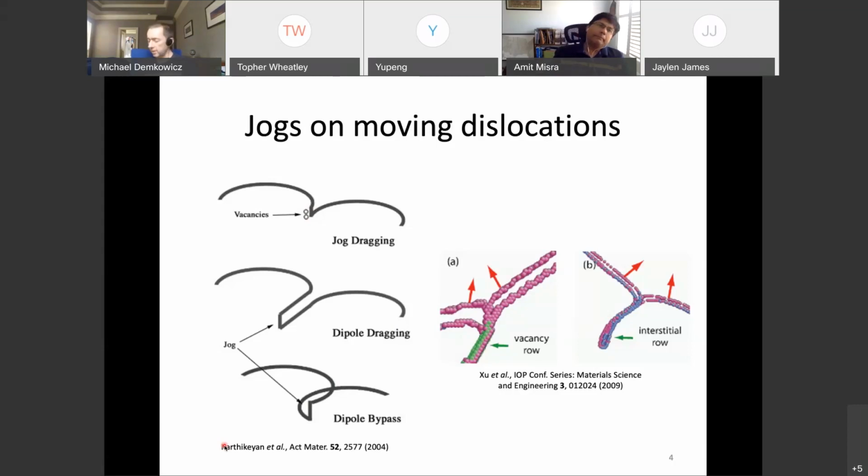I would say that all of those simulations are intended to solve different problems, right? So atomistic simulations are usually used to investigate core structures, or dislocation reactions, perhaps nucleation, things like that. Whereas dislocation dynamics and crystal plasticity are generally used to describe higher length scale collective phenomena such as hardening or texture evolution, or to solve boundary value problems in, for example, polycrystalline materials. Okay, thank you.